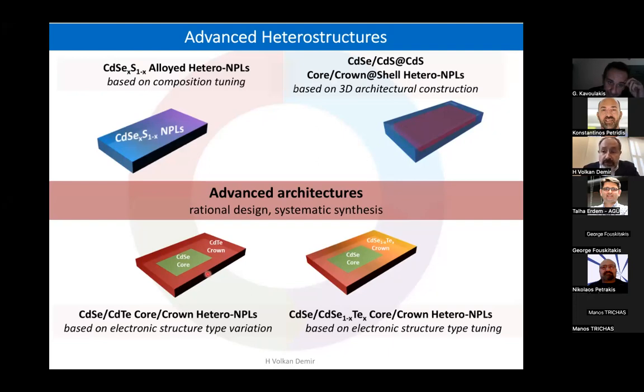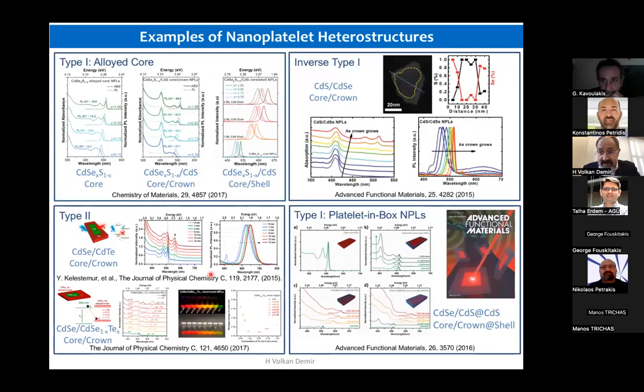One can also look into electronic band alignment, type 1 versus type 2. We can tune the band offsets and even use the geometry to our benefit. Although it should be actually type 1 band alignment, with the right geometrical structure, we can induce quasi type 2 behavior. So one can think about using different combinations of these, and that's exactly what we did over the years. Looked into alloyed core structures. We could actually reverse geometrically where we will confine electron and hole wave functions and generate what we call inverse type 1. This is the early work we did.